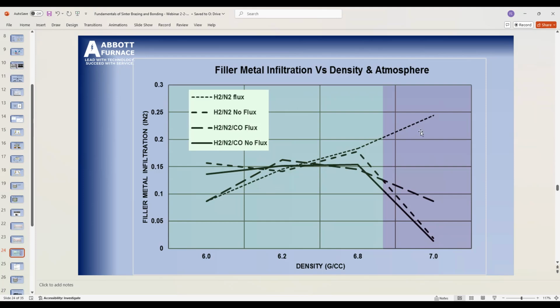And what we really want to be is in this range down here where we're not stealing it. It drops off. If we look at this black line, which is hydrogen, nitrogen, and our CO, which causes the carburization, and no flux, like I had mentioned, notice once we get above a 6.9, we don't lose that filler metal. There's little to no loss of the filler metal at the gap. It holds it right there. So what we put on there stays, and we can use it. Now, as we go up, you see that if you have the flux, we lose a little more, but if you have the CO, it works a little better than just having hydrogen and nitrogen by itself.